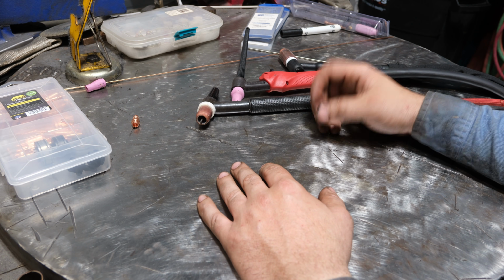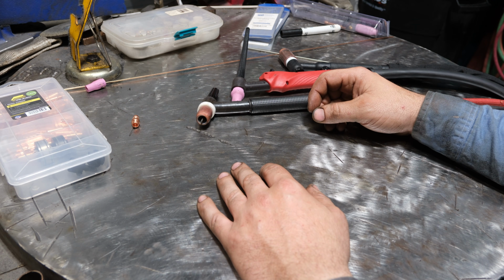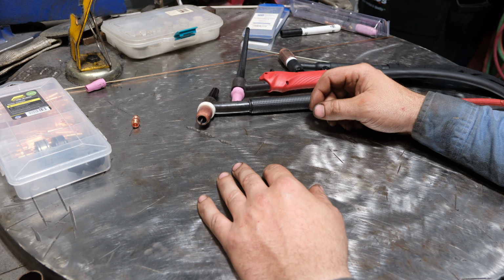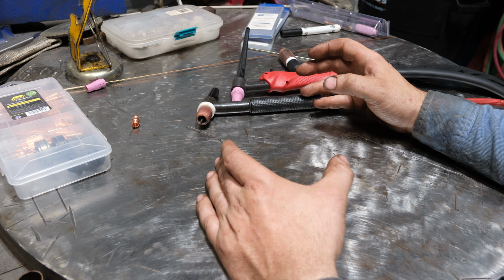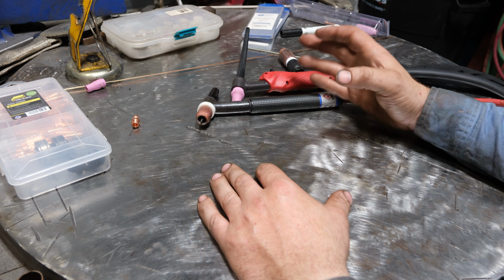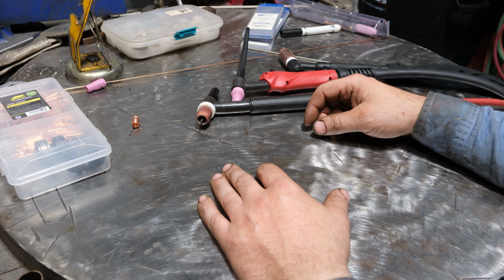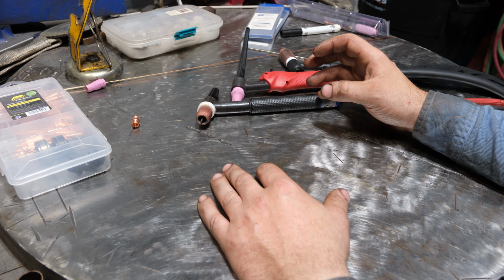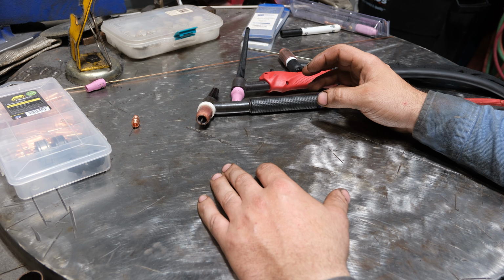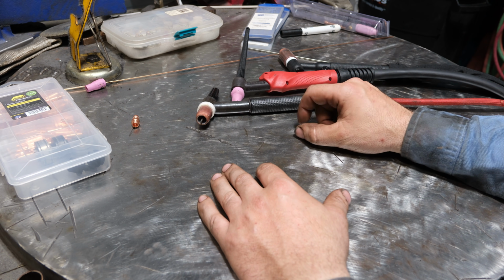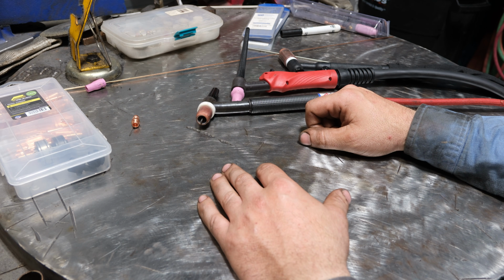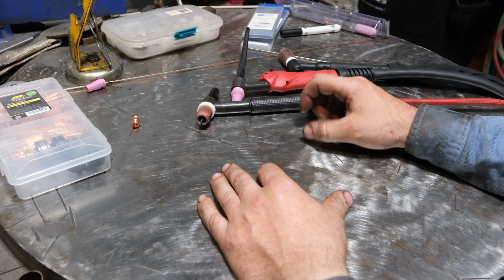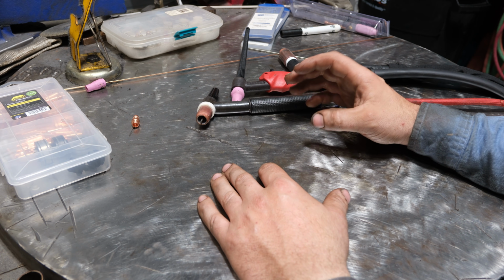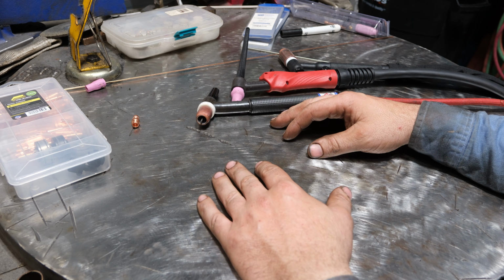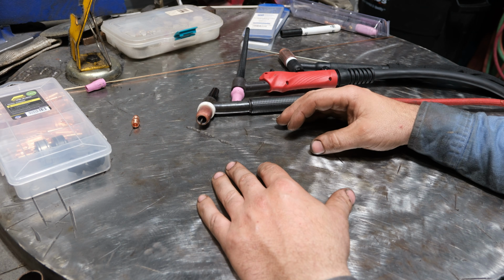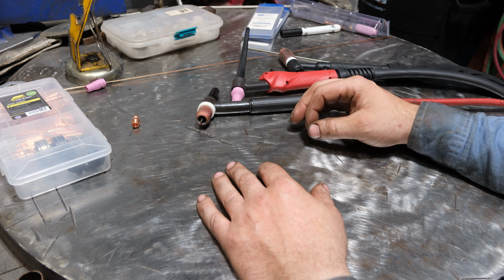You also have the great benefit of no post-weld cleanup. You don't have spatter if you're doing the process correctly. You don't have porosity generally unless you're welding over poorly surface prepped material or oils. And the heat input, depending on what you're welding, can be fairly high, but at the same time, because you can deposit smaller welds than a lot of the other processes, you can actually limit the overall heat input to where the temperature of what you're welding doesn't grossly exceed a threshold. So a great example would be tool steels can be welded with TIG welding, whereas a lot of the other welding processes would be far from ideal.